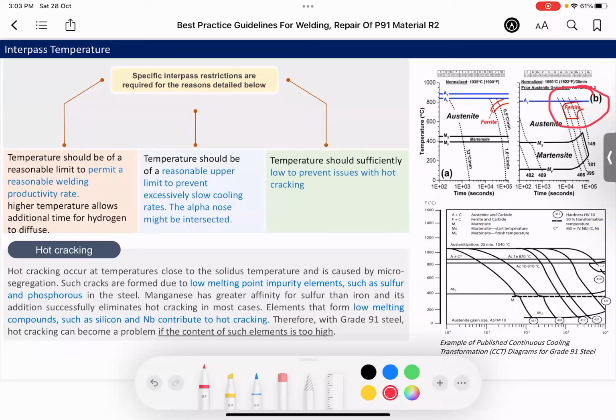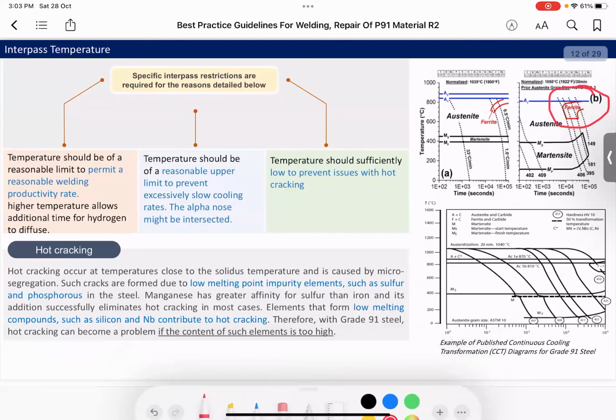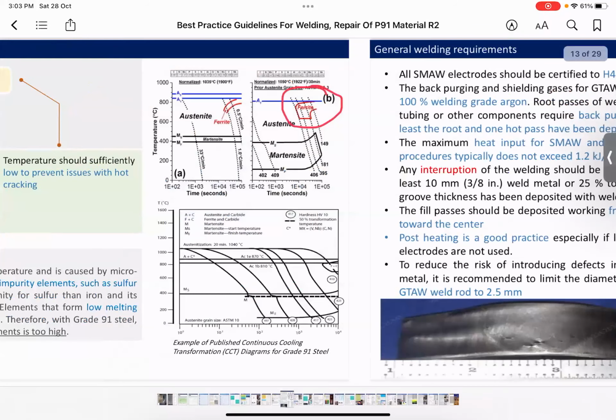So as I said, if it's too high, it can melt those elements like phosphorus or sulfur inside the steel and can create hot cracking if the content is too high. This is again a reminder that we should always verify the MTC and do PMI for the filler material.